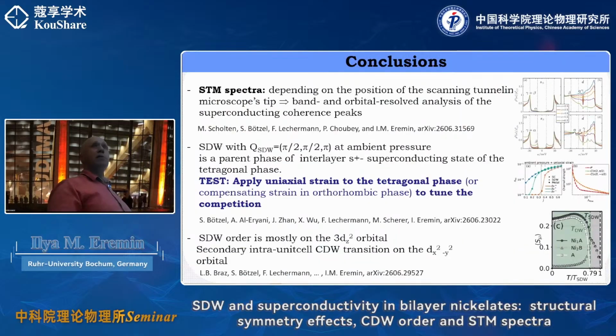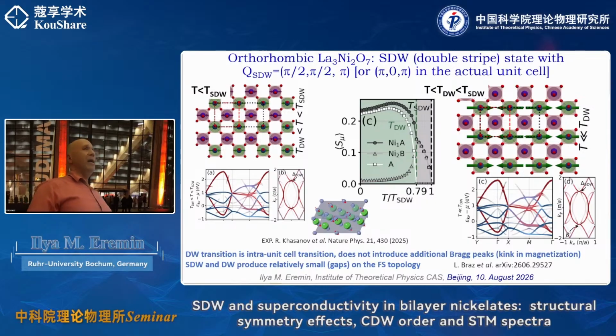I already discussed with Shenshun that there are still difficulties that we need to address. I have to say we did the calculation for the AM phase. Actually, we know now that the phase is AM2. I have an answer to that if somebody is interested. But in this case, what will happen is that from the very beginning, this green and red will already be different. They already have slightly different charge from the structure. So it means that an intra-unit cell charge order appears from the very beginning. So magnetic order sets in already in the presence of the charge order, and the actual transition of the charge order happens at much higher temperatures. So this is what we believe right now.